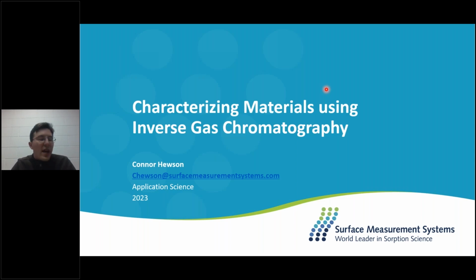So for most of today, we've been speaking about dynamic vapor sorption, which of course is a gravimetric technique used to determine the mass increase or decrease as we're introducing water or organic vapors in different flows, in different concentrations at steady states. Now I'm using a very different technique where I'm introducing those sorts of gases, but now as an injection, as a pulse, rather than as a continuous flow.